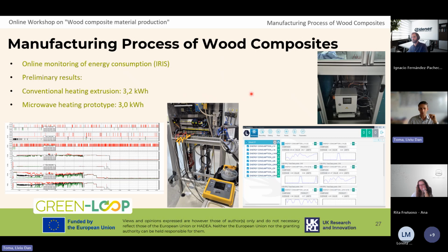Nevertheless, we were very diligent, and we also took a lot of time to check the energy consumption. For this, we had help from our partners in the consortium, IRIS, which provided us with special units to check the energy consumption, and the preliminary results show us, unfortunately, not such a big energy saving between conventional heating, extrusion, and microwave heating, which we're using in our prototype.